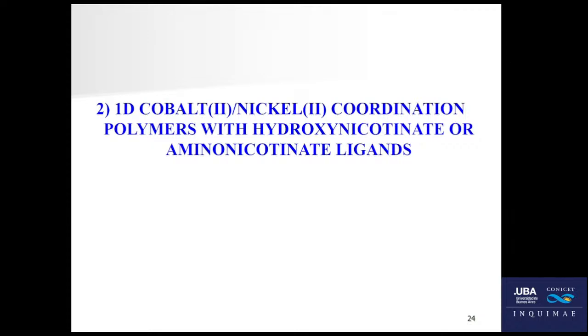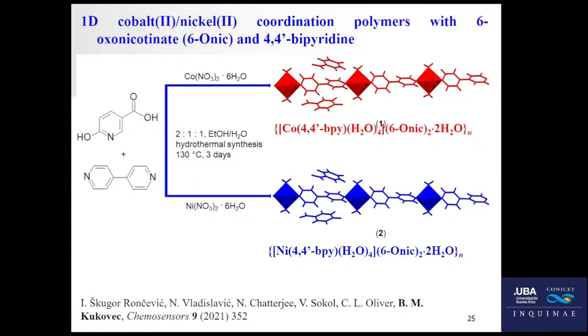So these were the selected polymers obtained with halonicotinate ligands. We also used some different substituents, as I said previously, like hydroxy and amino nicotinate. Here we have the synthesis of both nickel and cobalt coordination polymers, this time with 6-hydroxynicotinate ligand and the most simple 4,4'-bipyridine. The synthesis here was different from anything that I mentioned previously. We again used a mixture of ethanol and water, but under hydrothermal conditions. The reaction mixture was held at 130 degrees for 3 days. We put in 4,4'-bipyridine, the hydroxynicotinate ligand, and either cobalt or nickel salt, and we got